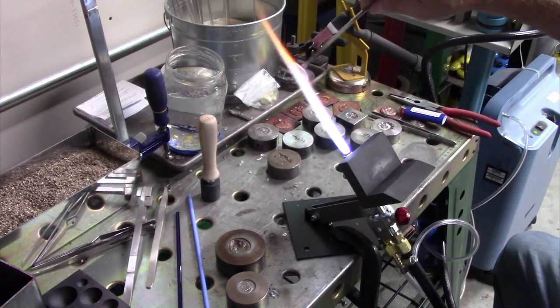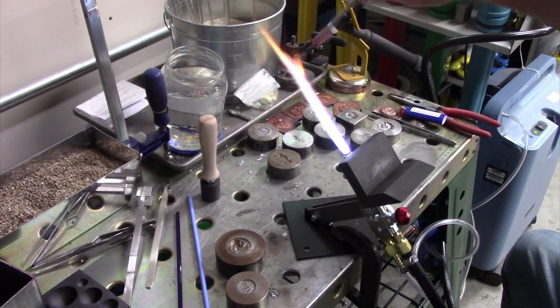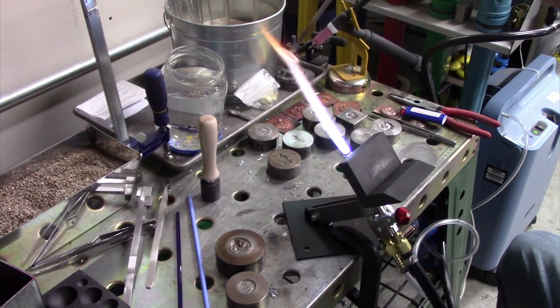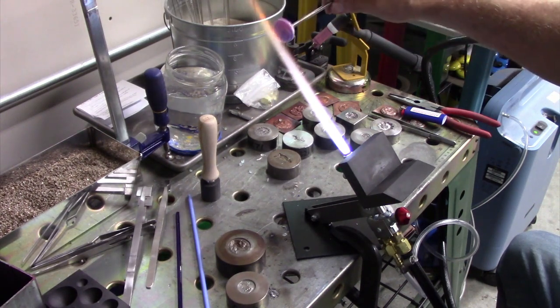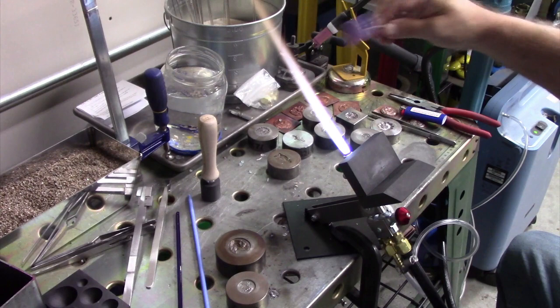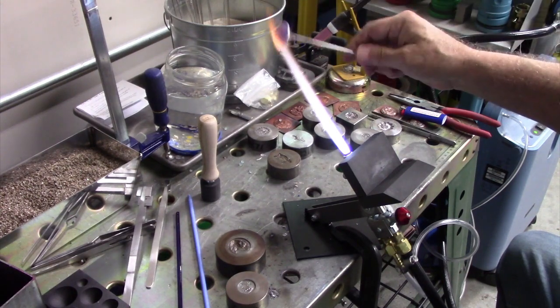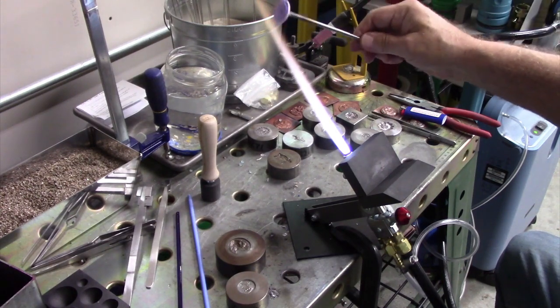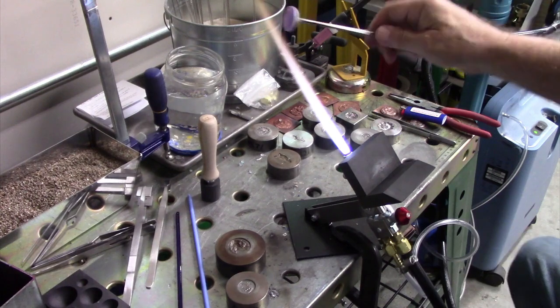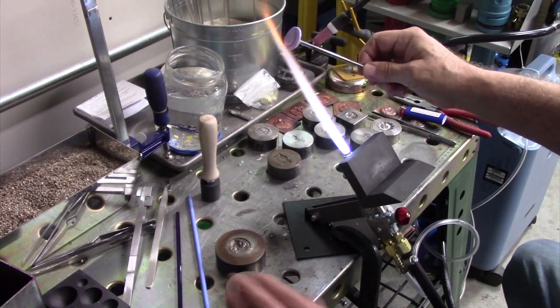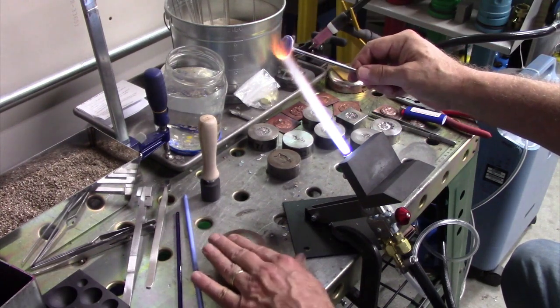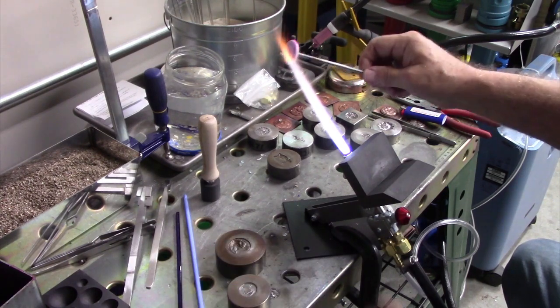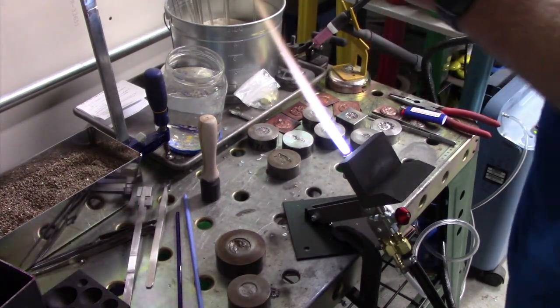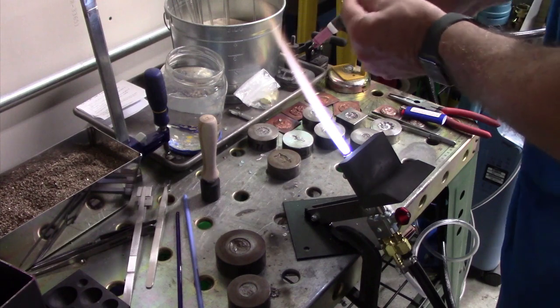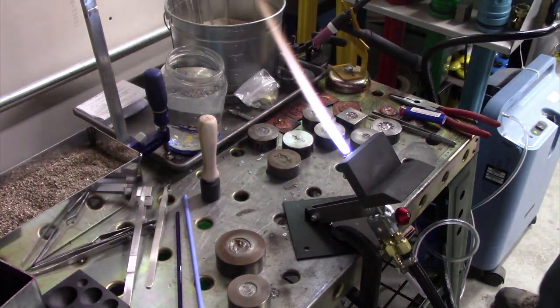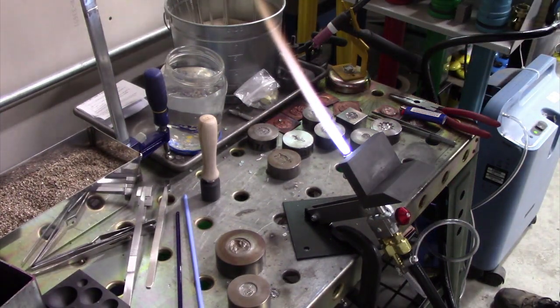But again, what you want to do is fire polish the chill marks. And I like to bring it back up a few degrees in temperature because, if I get it red again, pushing it into the steel die is creating one heck of a thermal change for the glass. And as long as the die is cold, or room temperature to start with, nothing's going to stick on it. In fact, it's cold back now. But now this is going to be closer to an annealing temperature that I'll put back in this vermiculite.